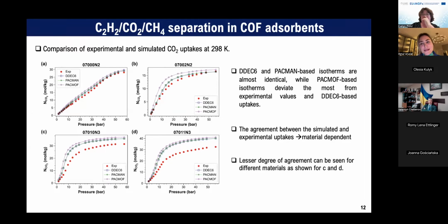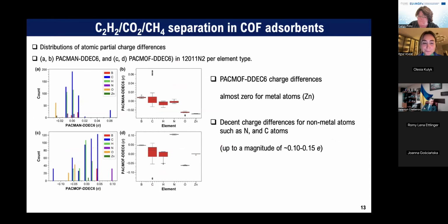So we see a lesser degree of agreement for C and D, and in simulation papers you can see this kind of discussion. We can have some discrepancies, and there can be many reasons for it. For example, we generally have perfect crystals in our models, but in reality we cannot have a perfect crystal, or the force fields that we use may not be so suitable for the structures that we are using. So you can think of many different explanations when you compare the simulated and the experimental results.